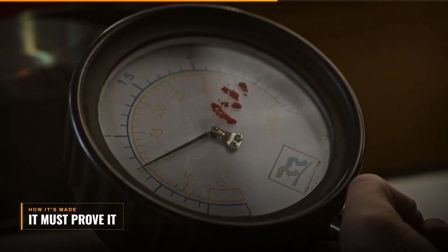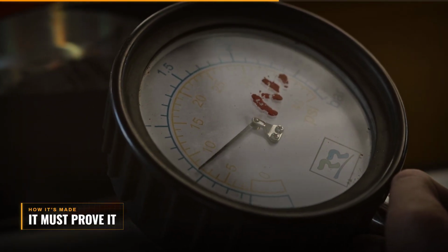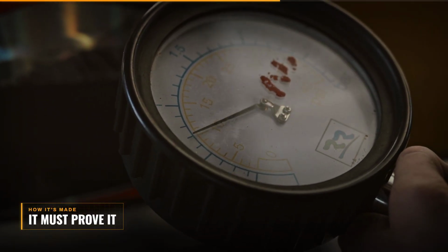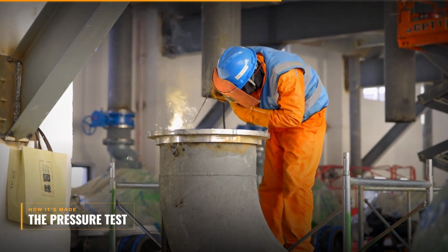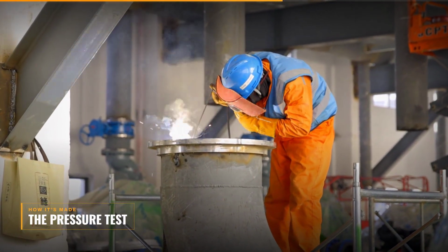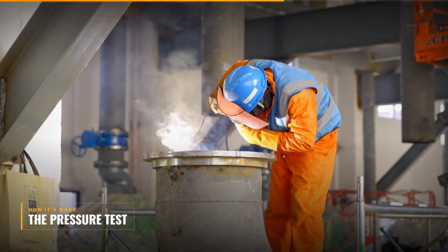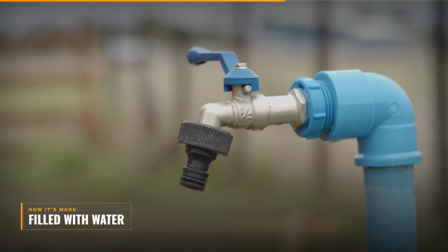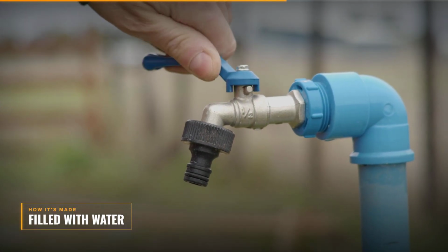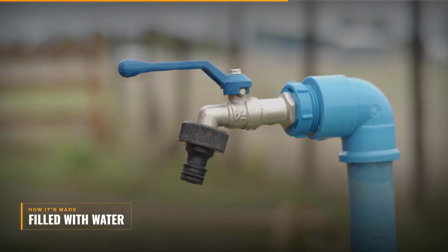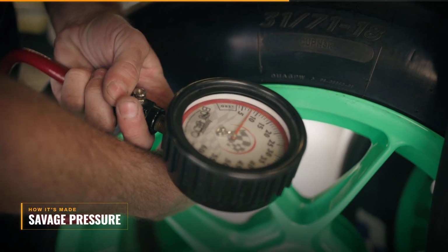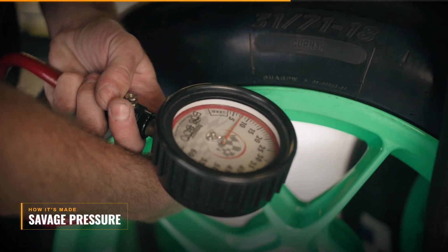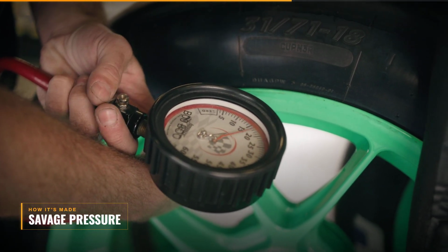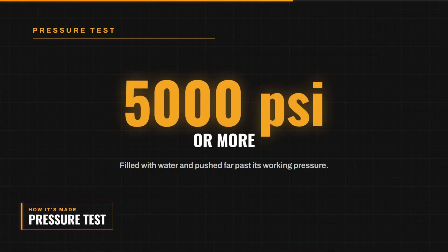Now this pipe might one day hold gas at crushing pressure, so it has to prove itself. It moves to the single most important test in the entire factory, the pressure test. Both ends are sealed shut, and the pipe is filled completely with plain water. Then that water is pumped up to a savage pressure, far beyond anything the pipe will face. Some line pipe is squeezed past 5,000 pounds of pressure per square inch.